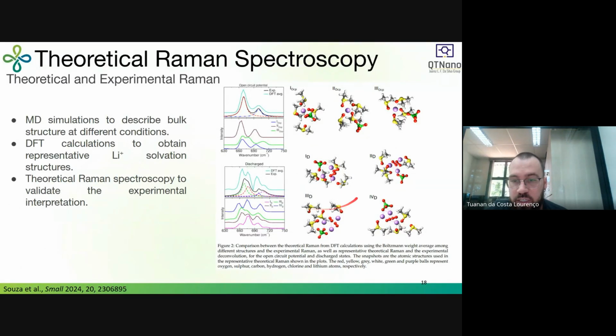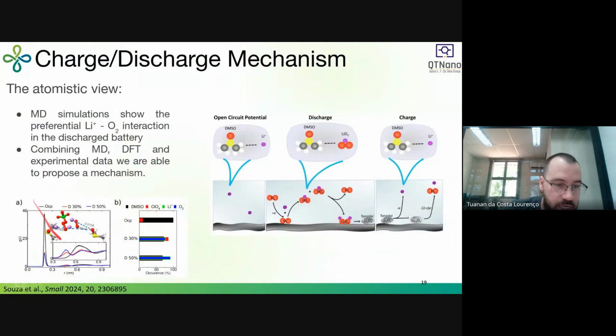So that means that when we discharge the batteries, the product of the discharging is now interacting with the lithium ion. And if we go to MD simulations, we can also see this behavior. So again, RDFs here. As we saw, if we have a high peak here, and this black is the charged system, and here we are looking at the interaction of the lithium ion and the DMSO molecule. So a high peak here means that we have a strong and close interaction between DMSO molecules and lithium ions. However, when we go to 30% of discharge and 50% of discharge, there is a decrease in this peak, so the DMSO is leaving this first solvation shell because the other ions are occupying it. And also we can see an increase in the second peak of the DMSO around the lithium. So that means that DMSO is in the second solvation shell.